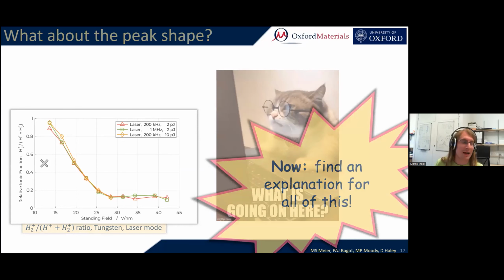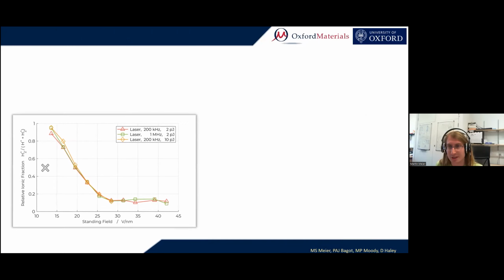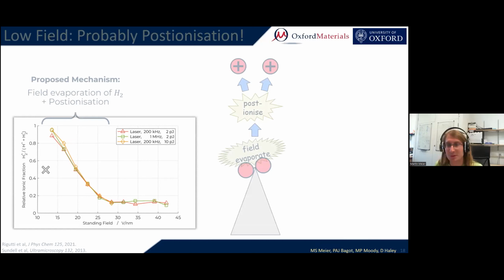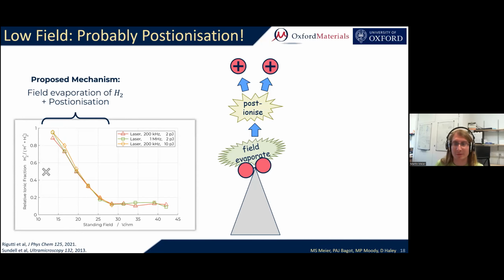Number one, I believe what we're seeing in this low field regime is an incarnation of post-ionization. So the way it would work is this. We have a hydrogen 2 that's adsorbed in our tip, and it's field evaporating, and eventually it's post-ionizing. Now, if you think about it, the hydrogen 2 molecule, so this thing here, it is only 2 protons and 2 electrons. So after post-ionization, both of the electrons are gone, and there are just 2 protons left. So there's nothing that could possibly hold this molecule together anymore, and it must immediately dissociate.